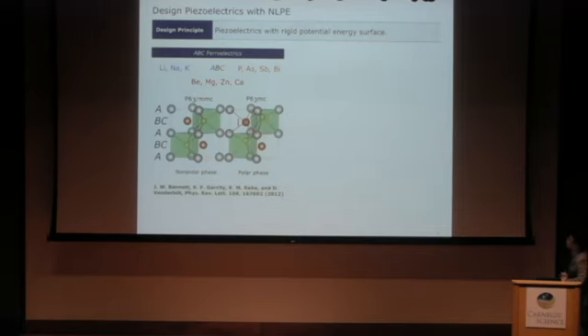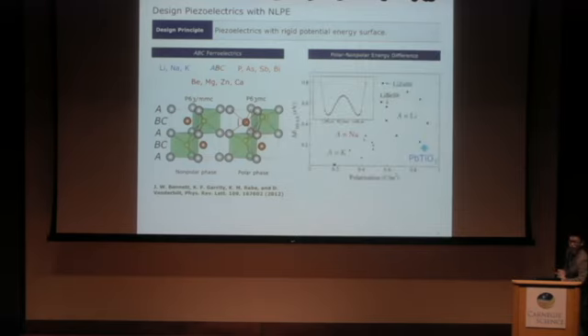It caught my attention because in the paper, they also calculated the switching barriers. This figure shows essentially the energy difference between the polar phase and non-polar phase. So this figure shows the switching barrier and energy difference as a function of polarization for all the ABC ferroelectrics they discovered with a first principles high throughput approach.